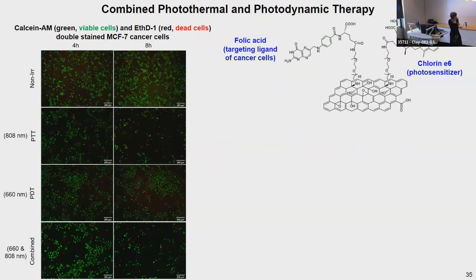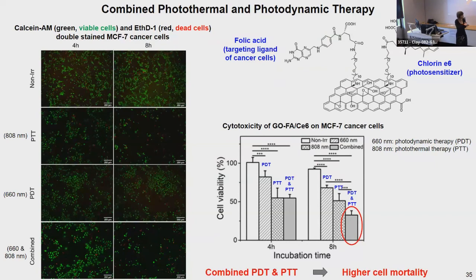This is also something that we could see, but to a much lower extent, when we performed the single photodynamic therapy by irradiating the cells with a laser at 660 nanometers, allowing us to excite the photosensitizer and generate the reactive oxygen species. When we combine the two treatments, then you can see that here there were much fewer cells. And we quantified the number of cells using a specific assay to determine the cell viability.